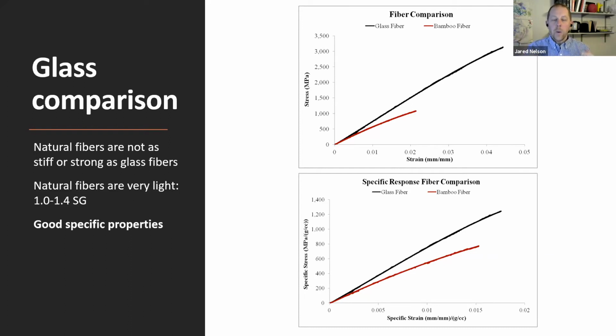Well, again, let's come back to that weight issue. One of the key factors I mentioned early on was regarding weight, and we know that the natural fibers are about half the weight of fiberglass. So if we look at specific properties, in other words, we divide our stress and our strain by density, all of a sudden we're looking at a much more competitive product. The stiffness, in other words, the slope of the lines, are still different. The bamboo is not nearly as stiff as the fiberglass, but we can see that we're getting a lot closer in terms of the strain at failure, and we're getting much closer in terms of the stress at failure. So we're seeing some benefits when we consider weight.